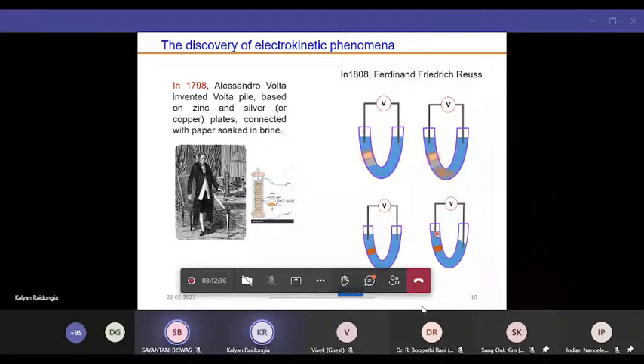Actually, what happens when we apply a voltage is that clays have negative charges, so only cations are allowed to go through the pores mostly. Once the ions have selectively gone from one side to the other, to compensate for the excess ions, water also follows through the osmosis process. So the water level increases. This is a very interesting experiment, and it is known to be the starting point of the electrokinetic phenomenon.